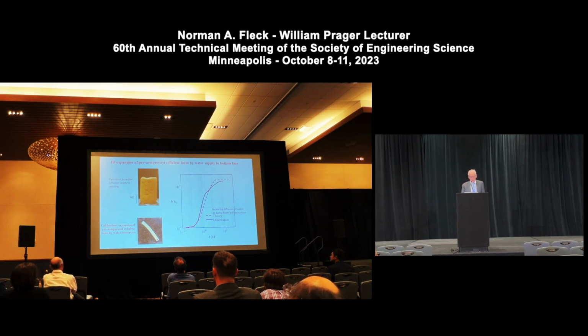That gives you a height against time curve, experimentally as shown, and one can develop a model. I don't have time to go into it, but the theory would talk in terms of diffusion of water through the damp foam, followed by actuation in order to expand it, to give you this large factor of 10 in terms of expansion of the foam. But time dependent for two reasons, the expansion and the diffusion.